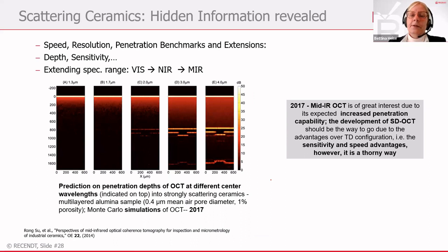It can also be approached from a different side. We can not only use mathematics, we can also improve optical settings. We can go to higher wavelengths, from typically the near-infrared range to the mid-infrared range. That also influences speckle patterns and the information we can see, or which is hidden, in the very left image, which is taken with an OCT at 1.3 micrometers, here in simulation.